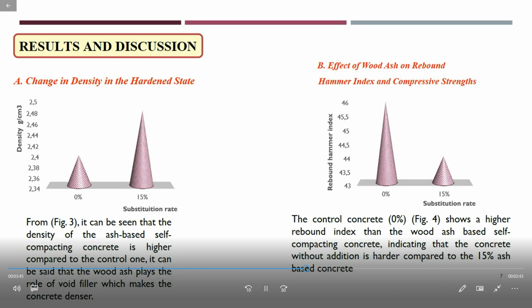Results and discussion: change in density in the hardened state. From this figure, it can be seen that the density of the ash-based self-compacting concrete is higher compared to the control one. It can be said that the wood ash plays the role of void filler, which makes the concrete denser. Regarding the effect of wood ash on rebound hammer index and compressive strength, we can see that the control concrete 0% shows a higher rebound index than the wood ash based self-compacting concrete, indicating that the concrete without addition is harder compared to the 15% ash based concrete.